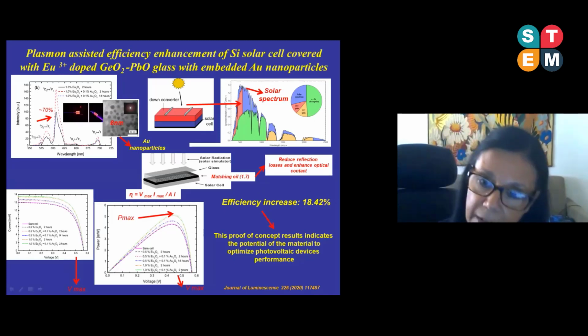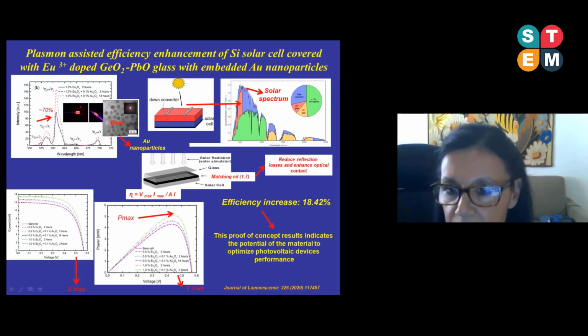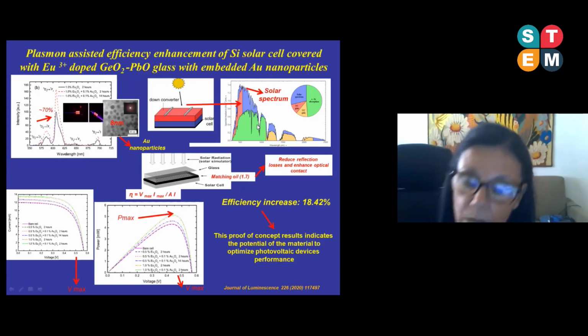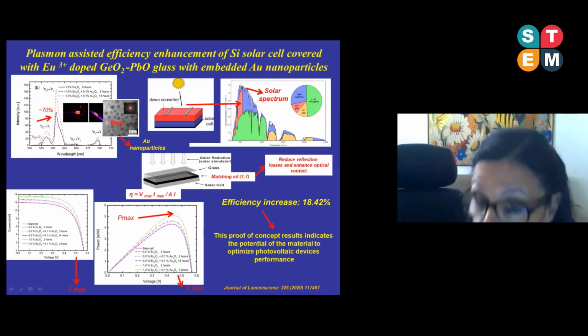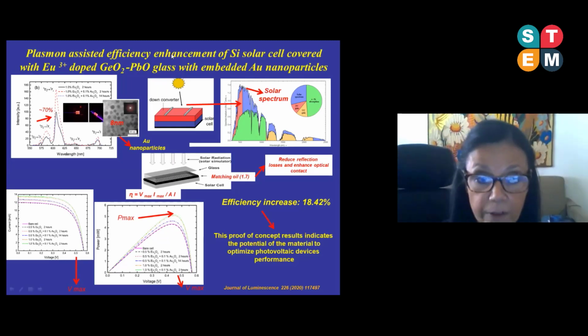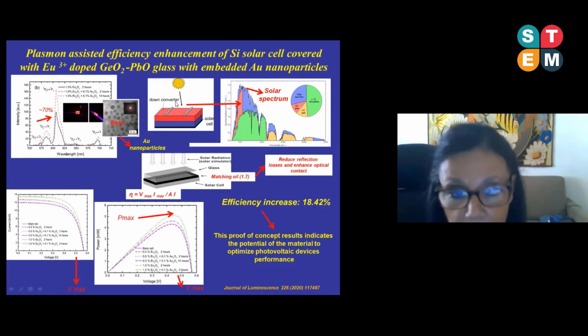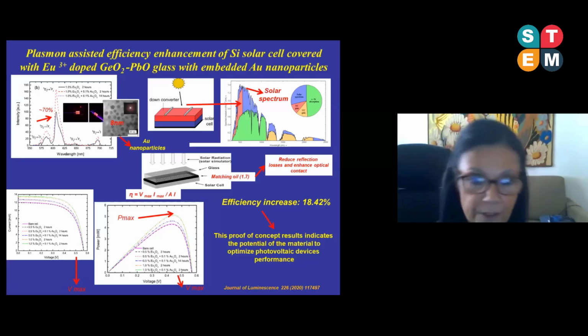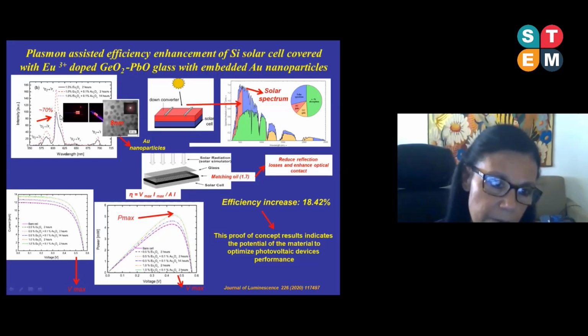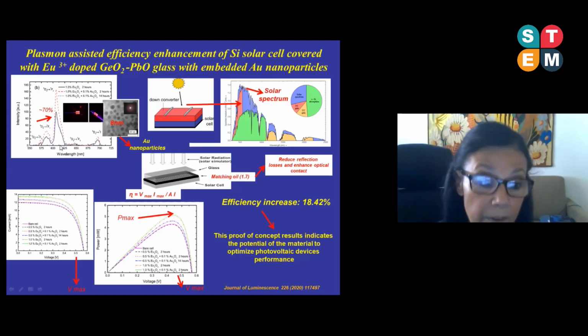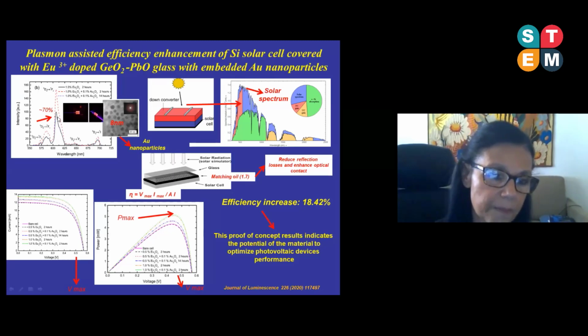There is always a mismatch between the solar spectrum and the silicon solar cell absorption, and a way to overcome this problem is based on covering the silicon solar cell with a luminescent material that makes use of the down conversion process. That was motivated by this interesting result that can be seen here, in which you observed an enhancement of about 70% for this important emission of europium, centered at about 600 nanometers, attributed to the presence of these gold